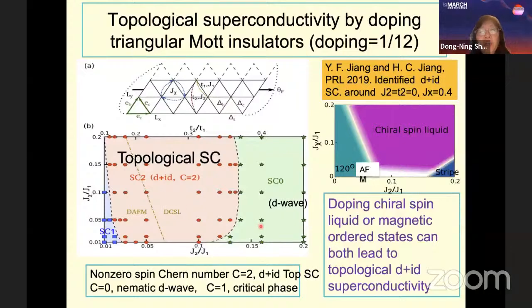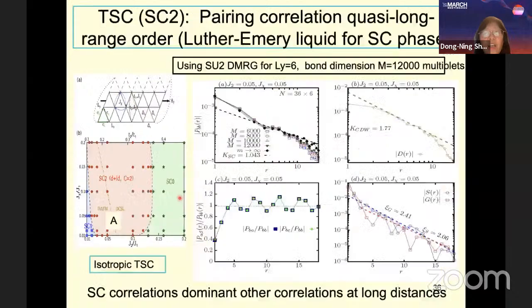If we have larger T2 over T1, then doping those chiral spin liquid or nematic spin wave states, we always obtain D-wave superconductivity. So it indicates topological superconductivity dominates the phase diagram when we move on to the triangular lattice.